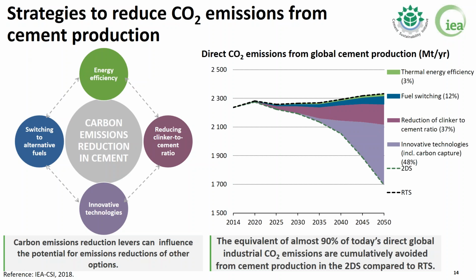One is our reference or baseline scenario, which we've called the reference technology scenario, as you can see here in the dotted black line. This scenario considers energy consumption trends as well as commitments by countries to limit CO2 emissions and improve energy efficiency, including NDC pledges under the Paris Agreement. And then we've developed a 2 degrees scenario with the ambition of limiting the global average temperature in the long term to 2 degrees.